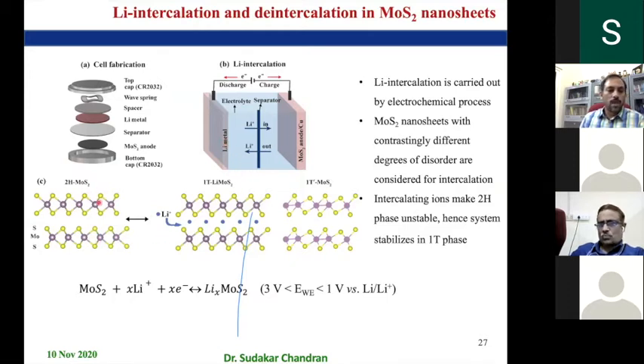So to start with, you have these molybdenum disulfide layers separated. Nothing is there in between the layers. When you intercalate, these lithium ions get in between these layers. And that's when the 2H phase converts to the 1T phase. Okay, and of course, once it gets converted to the 1T phase, it doesn't go back to the 2H phase. It remains in the 1T prime phase, where the octahedra is distorted. So here you have a distorted octahedra. In this case, you have an octahedral geometry. And using this, we wanted to see how the magnetic properties get altered.